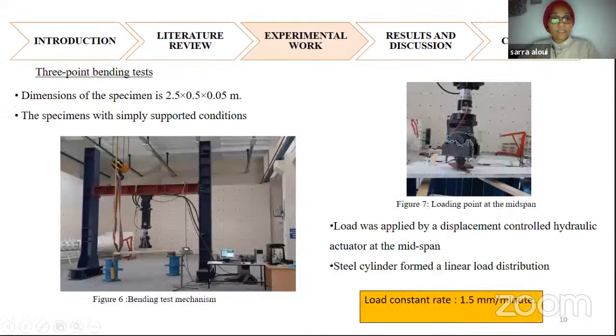To obtain the best results, 3 tests were executed in the laboratory. The first one is a 3-point bending test, where the beams have the dimensions of 2.5 length, 0.5 width, and 0.05 high, where the specimens were under simply supported conditions, as shown in figure 6. As well, a load was applied by a displacement-controlled hydraulic actuator at the mid-span, through a steel cylinder that forms a linear distributed load.